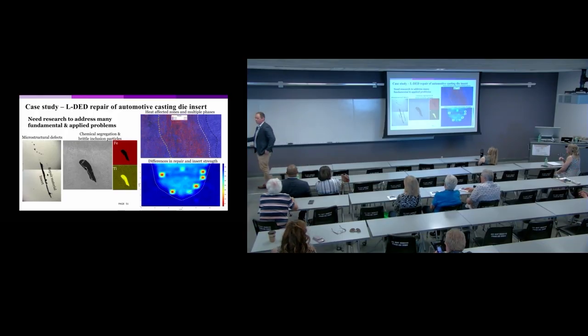But these are things related to the manufacturing, so misalignment when we put it in there, non-optimal process parameters. We have metallurgical challenges, so things like oxidation here. So you can see some titanium oxide, these brittle particles that have formed because of oxidation of molten metal. We also have mechanical challenges. So over here we can see a hardness map that we took from the repair. So the repair is actually much softer than the surrounding parent material.